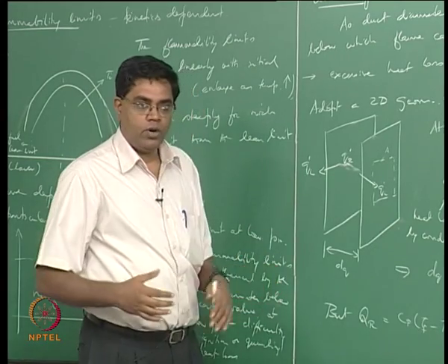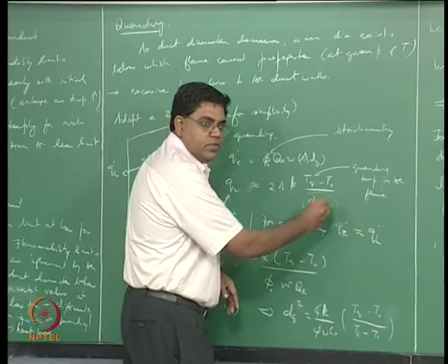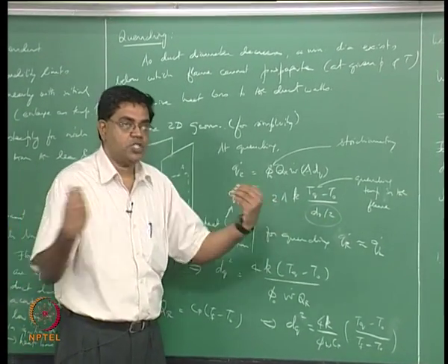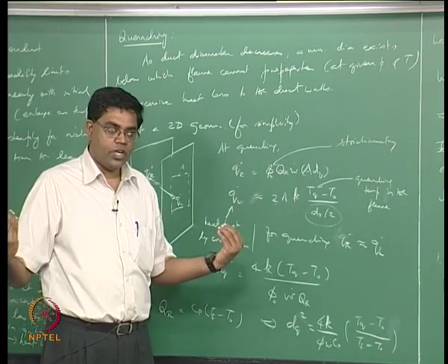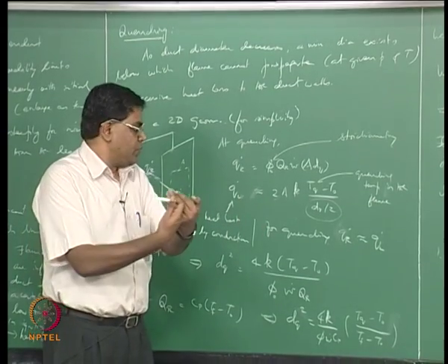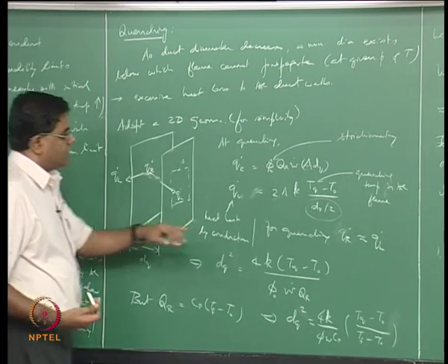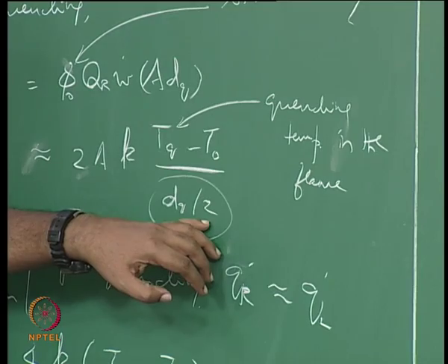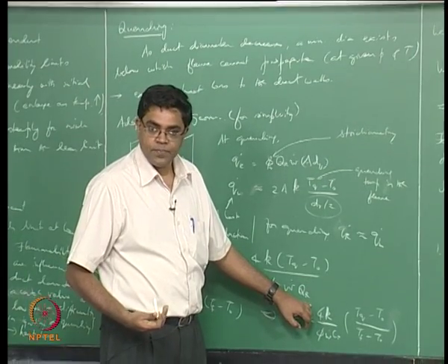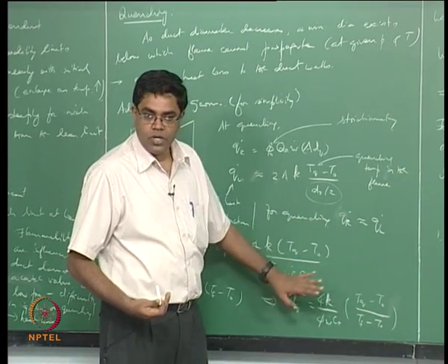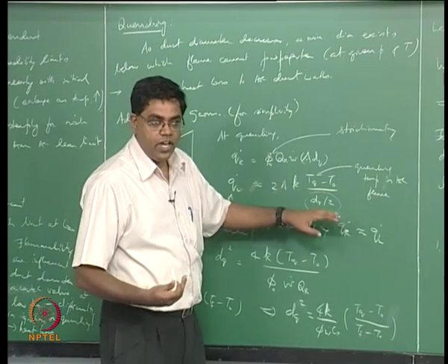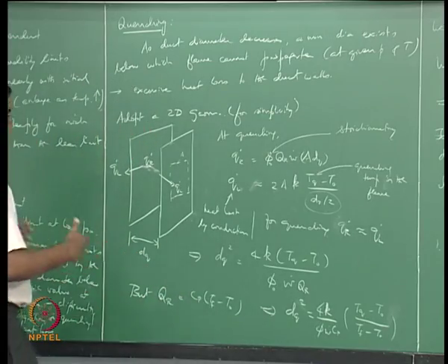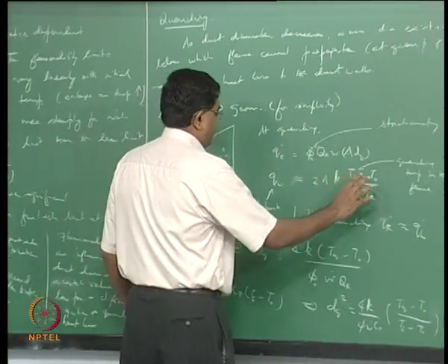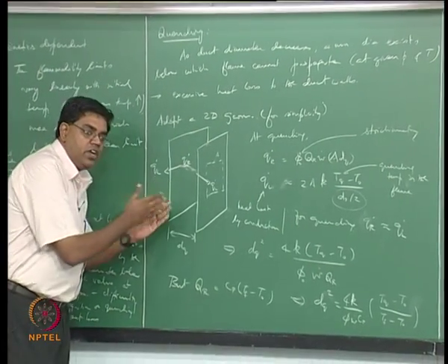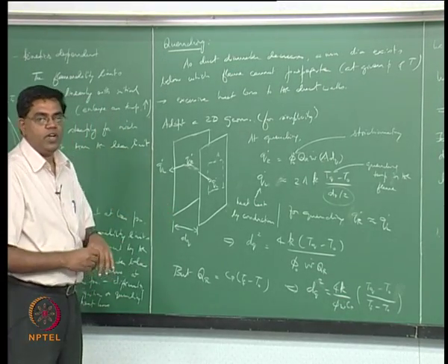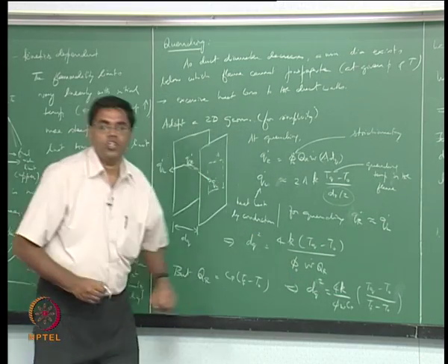But empirically, if you think about this, this is not really 2, it turns out to be actually more than 2. That means you don't necessarily have to have a large penetration distance. Okay, you don't have to actually have a penetration all the way to the middle of this. This is significantly larger than 2. Okay, so you're not going to get something like 4. It could be much more than that. We are okay on an order of magnitude, but this could be like, for example, 8. If it's 8, it's about off by 4 times, you see. So 4 or 5 times is typically how this is going to be. So as a first cut, we would like to think this is what it is. But you don't need to necessarily penetrate that much. Even a little bit of penetration of the heat loss is sufficient to actually bring down the temperature to a TQ, which is going to quench this, right?